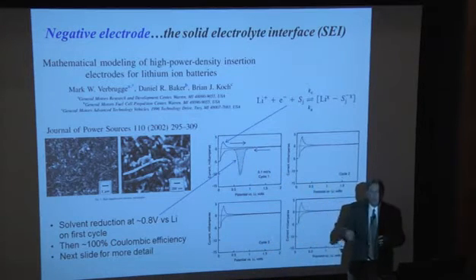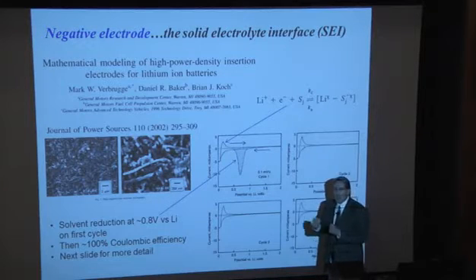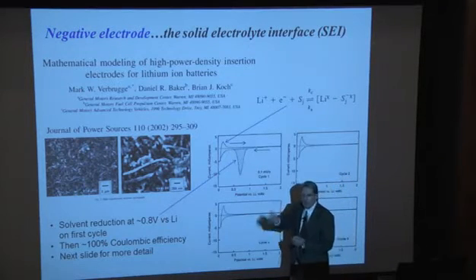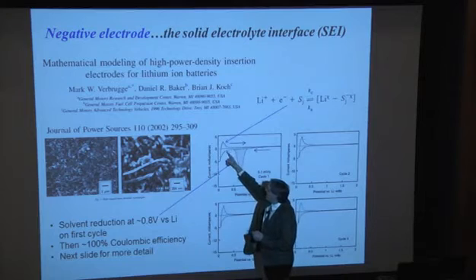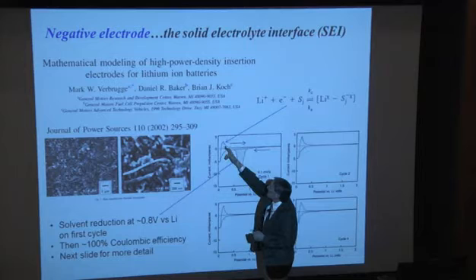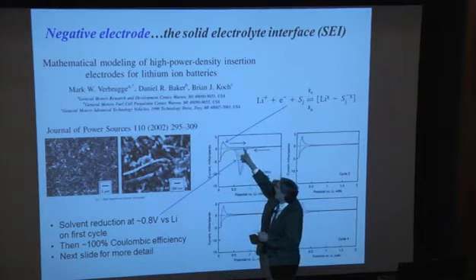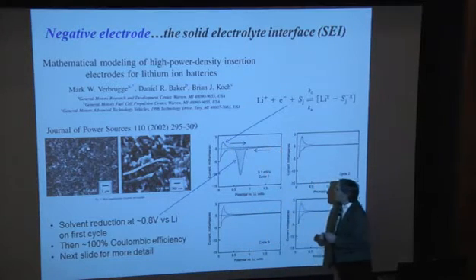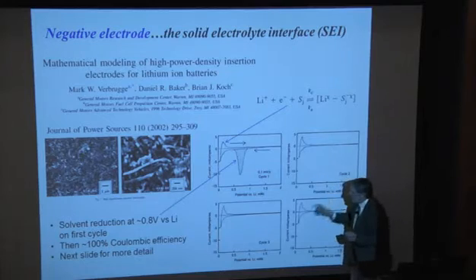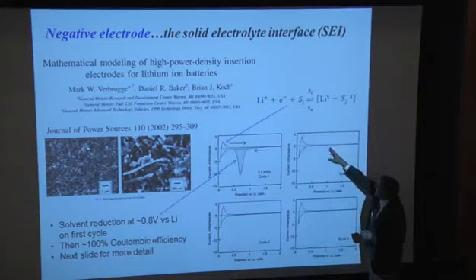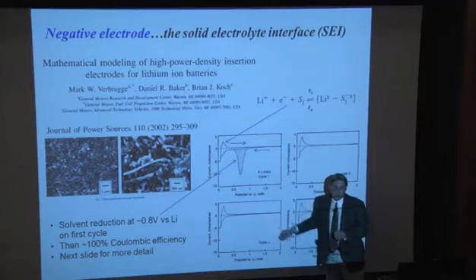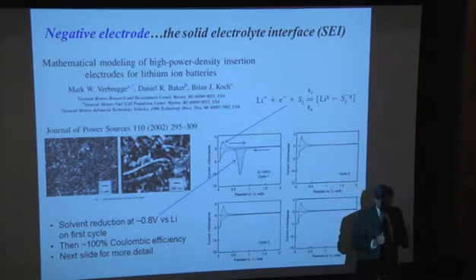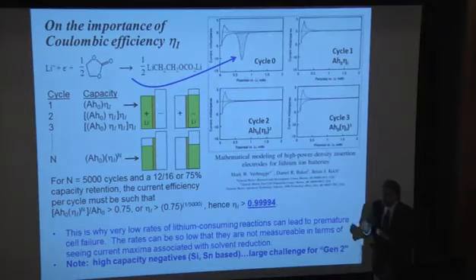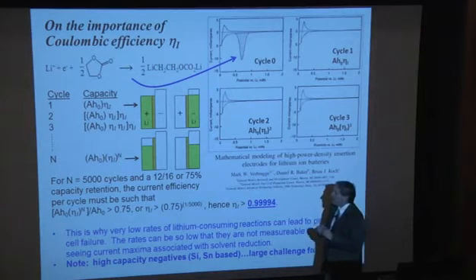You generate a bunch of bubbles. You see ethylene gas coming off. You're destroying your ethylene carbonate, liberating ethylene gas. And then you get down to this region where now you are actually inserting lithium and then deinserting lithium. So that's the reaction you want in the battery. And then you come back, we've taken all the lithium out. You've deinserted it all. Look at cycles 2, 3, and 4. You can't even see any evidence whatsoever. That's the beauty of a lithium-ion battery. This solid electrolyte interface forms on the surface, and it passivates subsequent reaction.